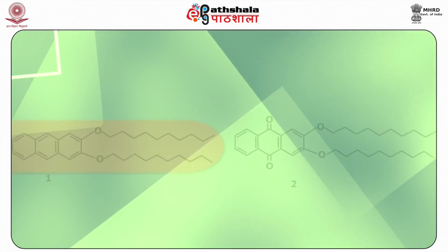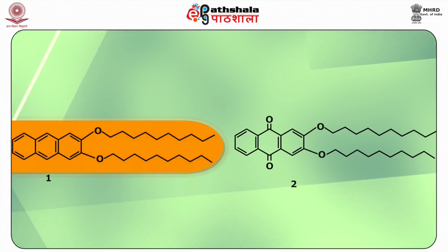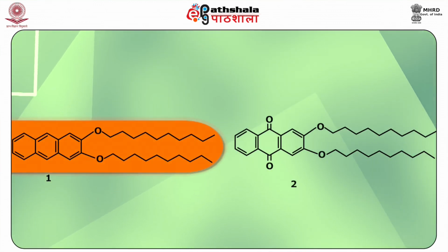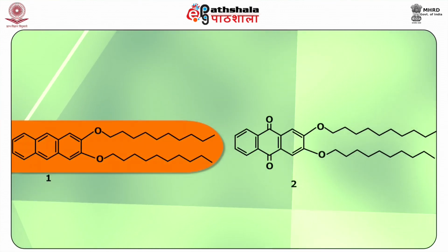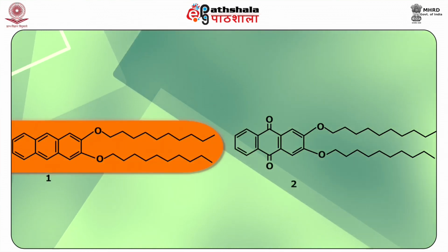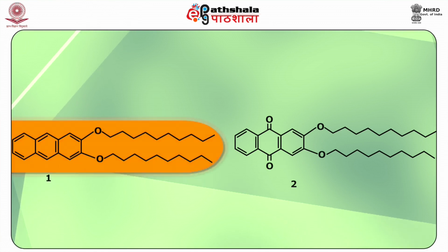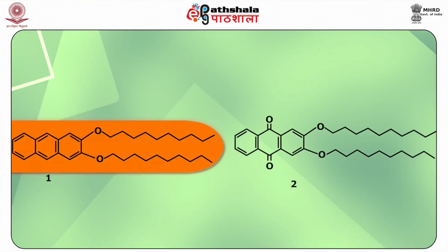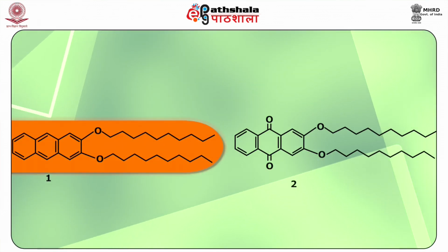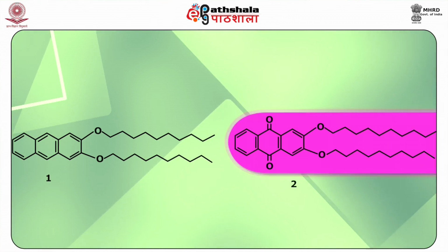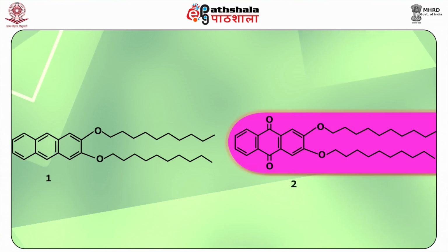Different types of compounds given below have been used as one-component organogelators. Anthracene derivatives. The compound 2,3-bis-n-decyloxyanthracene is a good organogelator and works at low concentration for a wide range of solvents ranging from alkanes to alcohols, ethers, ketones or halogenated molecules. The molecules of structure 1 are self-associated by van der Waals interactions and dipolar force. This gelator also has the ability to grow organically modified hybrid silica fibers. Another anthracene derivative, 2,3-bis-n-decyloxyanthraquinone, as shown, is also an efficient gelator of organic solvents.